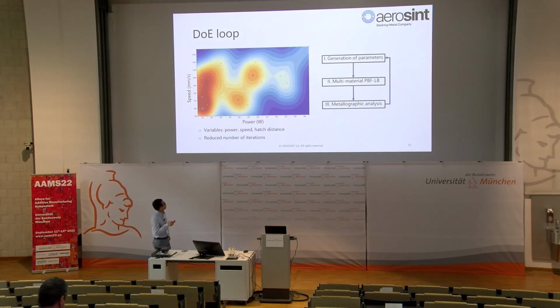So how it works is quite simple. Either the software will give you starting parameters, or for materials which have already been studied by others, you can look into the literature values. Then you go to the multi-material LPBF process, do the analysis just to check the density, and then give the results as feedback to the software. With the existing results, it will suggest other parameters, like in this graph you can see. The dark red color is the high probability region the software suggests, but you still see other discrete areas. It also needs data input. What we have changed is mainly the laser power, scanning speed and hatch distance, because these are the three main parameters also very relevant for productivity.